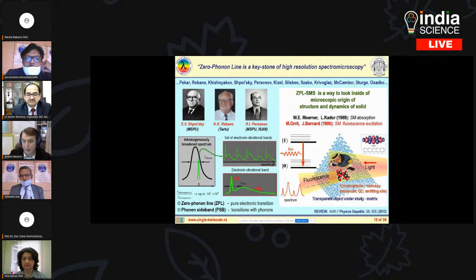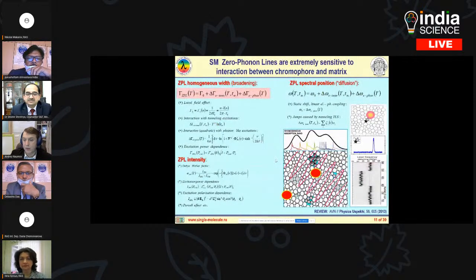And it is very interesting that at low temperatures, we can measure this very, very narrow spectrum, which corresponds to the pure electronic transition in such a molecule. Thus, we can do the following. Of course, there is very difficult, strong and extended physics around this phenomenon, because we need proper theories to describe the temperature and temporal dependence of parameters of such a spectrum, because each molecule interacts with the local surrounding, and we need proper theories to describe this interaction.